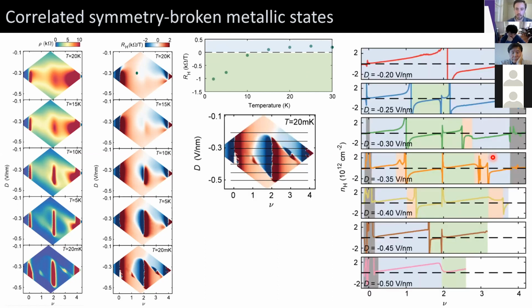We can investigate this in a bit more detail by looking at this map at 20 millikelvin and measuring the Hall density at fixed displacement field as a function of filling factor for different displacement fields. So the Hall density is just basically 1 over the Hall resistance. And what we find is that outside this halo region, it basically behaves as we anticipate from single particle expectation.